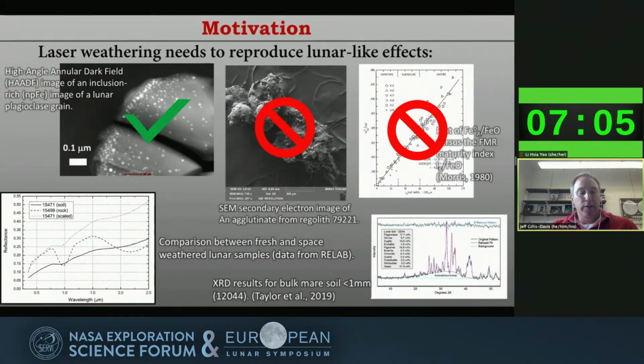Here on the plot in the lower left, you'll see there are 3 spectra. One is of a rock, the dotted line. And you can see that for a lunar, in this case a Mare rock, we have a very good absorption band at 1 and 2 microns showing pyroxene. But as we look at a soil that has been naturally space weathered on the surface of the moon, but is of similar composition, the black line there, you can see that those mafic absorption bands have now almost disappeared. The spectrum is darker, it's lower down.